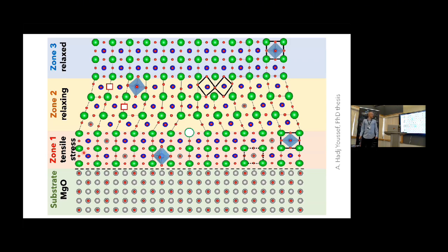Now we come to the end. After we see in elastic regimes, we have a nice curve. What is actually happening in the plastic regime where we get the unpredictable spiking? There's a nice graphic. On the bottom, we have this MgO substrate, and the first strontium titanate cells are able to stretch themselves to fit on the 4.2 angstrom. But at some point, when there are too many layers, the stored elastic energy is so high that it's easier for the system to create dislocations and start relaxing.